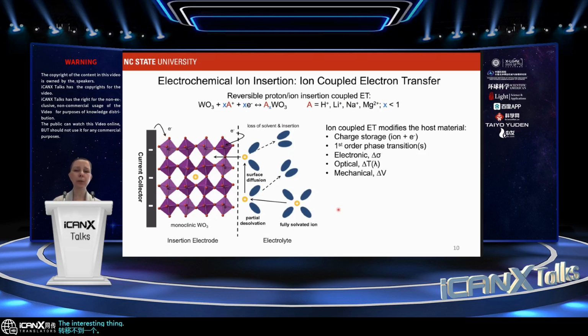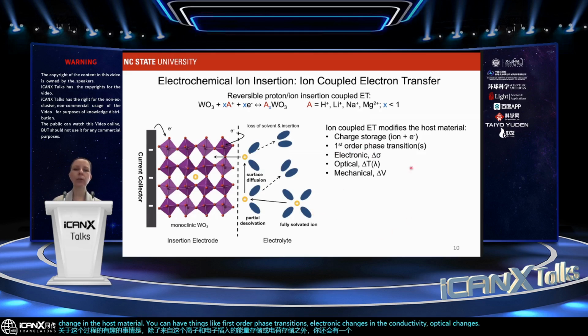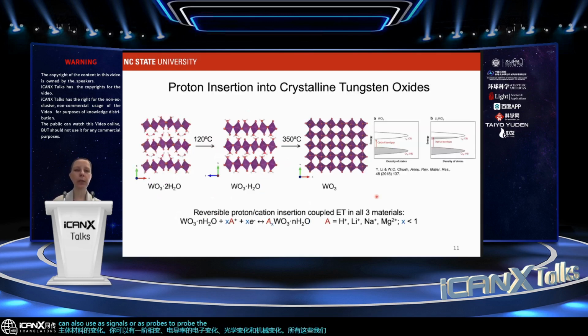The interesting thing about this process is that besides the energy storage or the charge storage that comes from this ion and electron insertion, you also will have a change in the host material. You can have things like first order phase transitions, electronic changes in the conductivity, optical changes, and mechanical changes. And all of these we can also use as signals or as probes to probe the charge storage mechanisms.